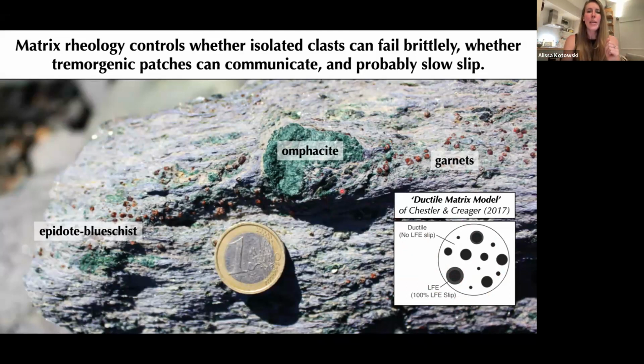But the problem is that these little asperities cannot explain all of the energy that we know is released during an ETS event. They can barely explain half of it at best. So this very simplified ductile matrix model, where this surrounding ductile matrix is not contributing to these LFEs, is probably actually not realistic. We need to think about what this matrix material surrounding these asperities is actually doing, because the rheology of this matrix is fundamentally going to control how much stress these little clasts can actually support. And it's also going to control whether these little asperities can actually link up and communicate to potentially create that avalanche or that cascade effect.